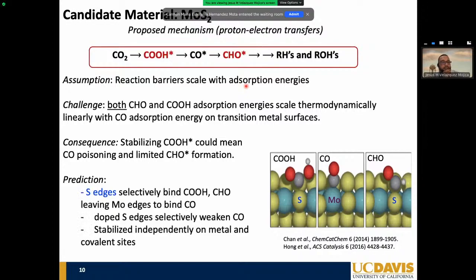And the hypothesis stated by Jens is that we could break scaling relations that we have with key intermediates if we have another center in which we could share the binding of key intermediates like CO and CHO. There's also some promise that by doping some of these materials, we could selectively impact the strength of that binding. And this goes back to what I was hinting earlier about the Goldilocks principle, of not too strong, not too weak interactions between your intermediates.